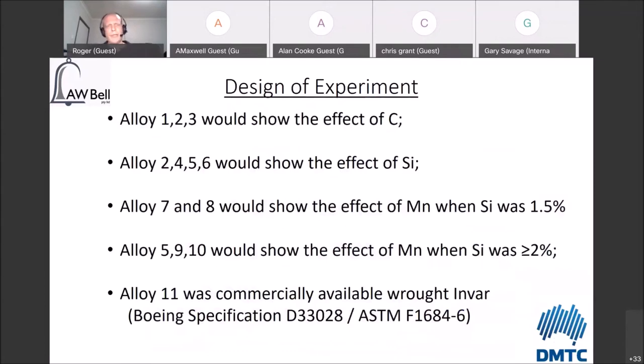The design of experiment was that alloy 1, 2, and 3 would show the effect of carbon. Alloy 2, 4, 5, and 6 would show the effect of silicon. Alloy 7 and 8 would show the effect of manganese when silicon was about 1.5%. Alloy 5, 9, and 10 would show the effect of manganese when silicon was greater than or equal to 2%. And then alloy 11, as already mentioned, was a commercially available wrought Invar according to the Boeing specification.